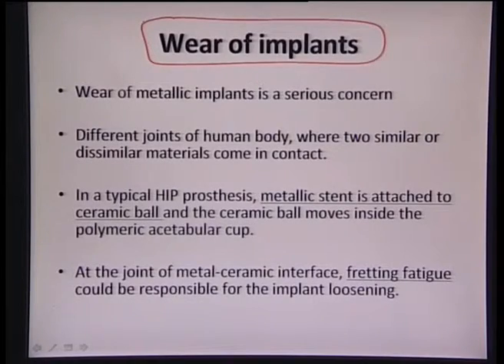Like we have acetabular cups and a ball and socket joint. In that we can see an overlay between a metallic surface and a polymeric or a ceramic surface. Once we have two dissimilar materials close to one another, definitely there will be some wear at the interface. Wear of metallic implants is a very serious concern, because once it starts releasing debris while getting abraded or worn out, those ions will start getting released into the body. And this wear will occur at the different joints of the human body.